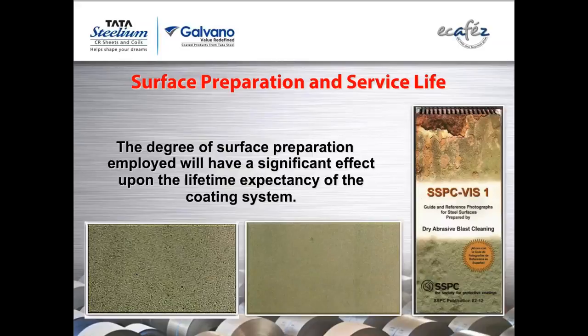Now, surface preparation and service life. This is very important to remember. The degree of surface preparation employed will have a significant effect upon the lifetime expectancy of the coating system. In marine industries, usually they spend almost an equal amount on blasting as they spend on the coatings. With three coats, the cost comes to almost the same. Here, basically, we are trying to save money on blasting.